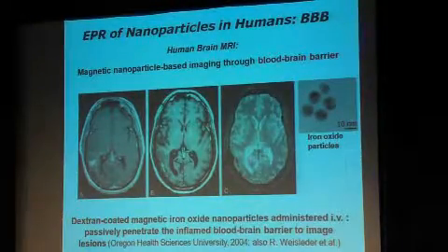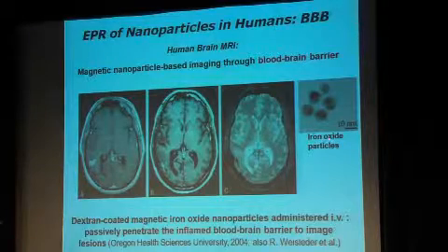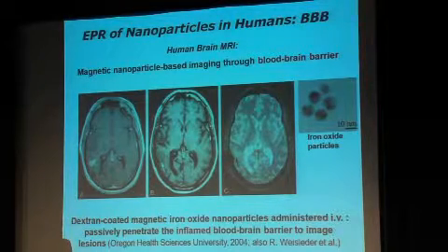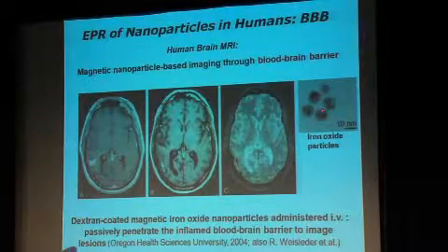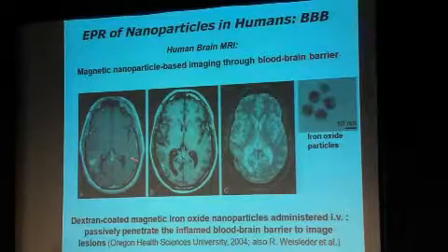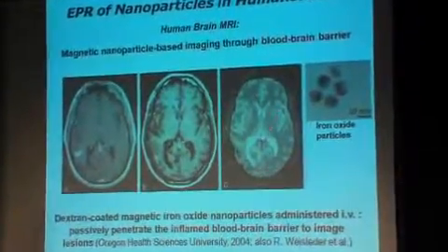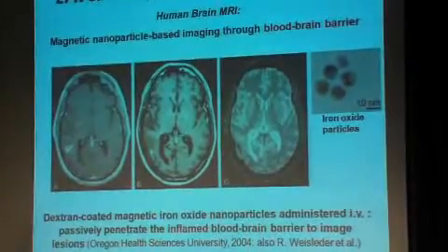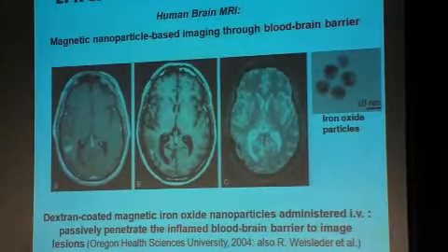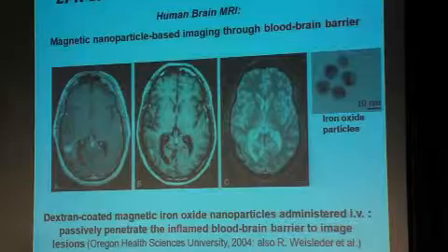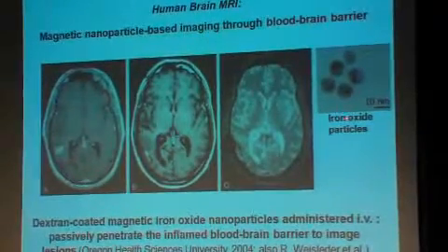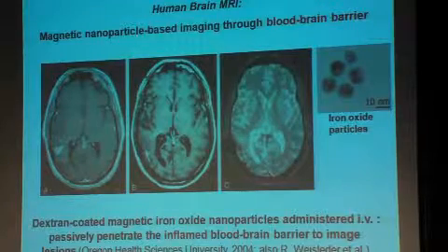So this was an interesting case in which commercial iron oxide nanoparticles, 10 nanometers, coated with a little slimy, slippery substance to keep them circulating so they won't coagulate out. These were injected into a human, and this is an MRI of a human brain, time-lapse, showing the development of images that show very nice lesion and structural physiological identification within the brain.